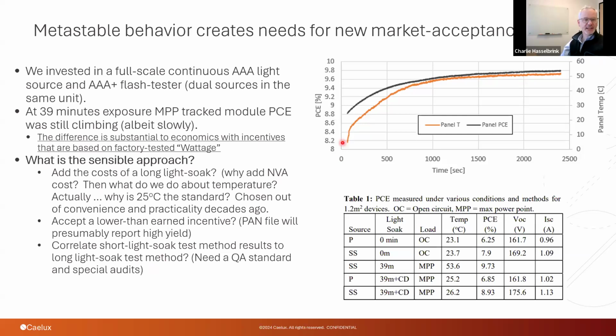Thirdly, you could correlate a short-term light soak test. If these curves are repeatable, and you can demonstrate correlation between this data point, let's say, and this data point here after a short amount of time, and maintain it constantly and do this test periodically on a representative sample or a random set of samples, and prove that to auditors, then maybe that's another way to go. That would give the benefit, of course, of more accurate measurement for incentive purposes without having to pay all the cost of these long light soaks.